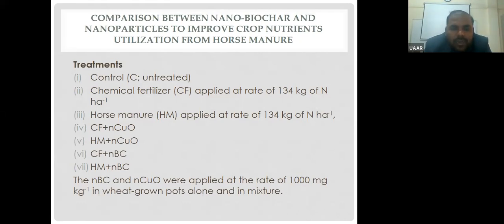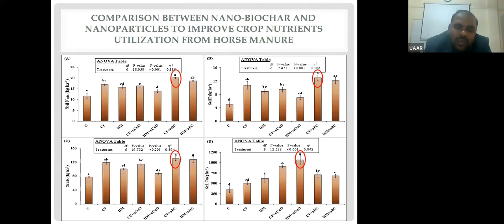Both copper oxide nanoparticle and NANO-BIOCHAR of horse manure were applied at the same rate in the pot experiment. And if you look at the results, they are very interesting. Chemical fertilizer along with NANO-BIOCHAR improved soil nitrogen mineralization, soil available potassium, soil available phosphorus. All 3 nutrients NPK were improved only with the chemical fertilizer and NANO-BIOCHAR. However, if you look at the horse manure with the nanoparticles, they have a negative impact here when horse manure was mixed with nanoparticle at the rate of 1000 milligram per kilogram of soil. This metal now has a toxic effect when mixed with organic fertilizer.